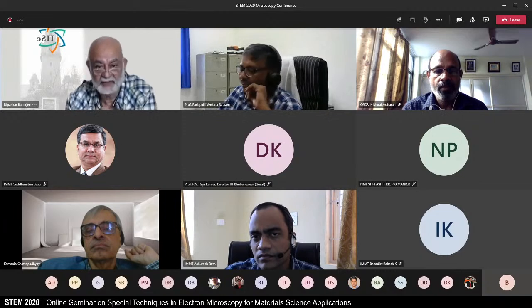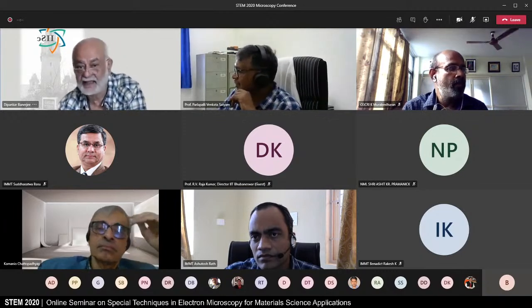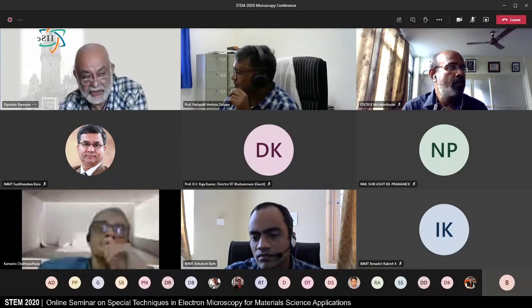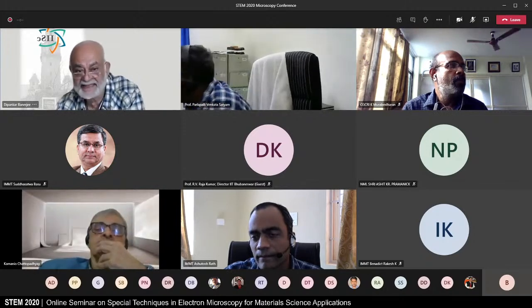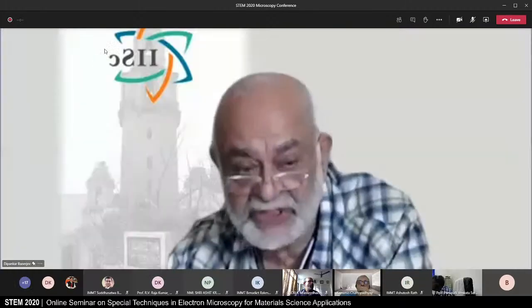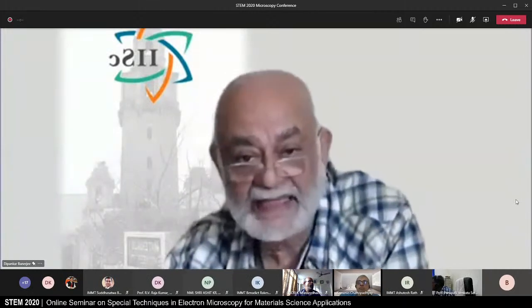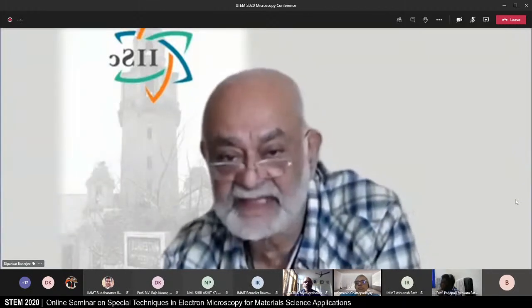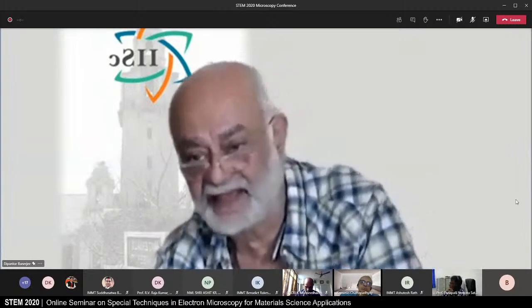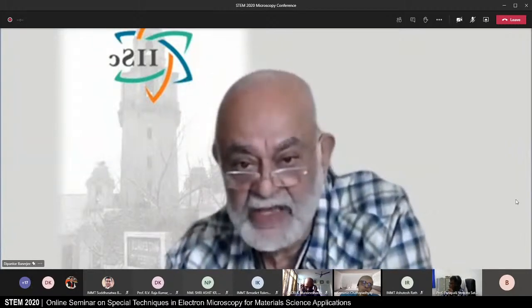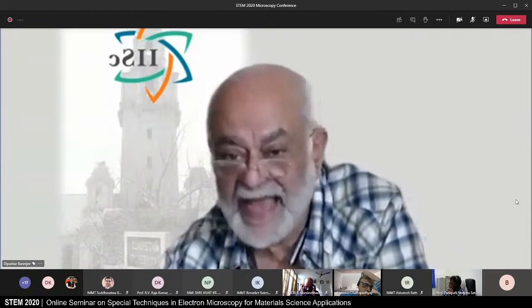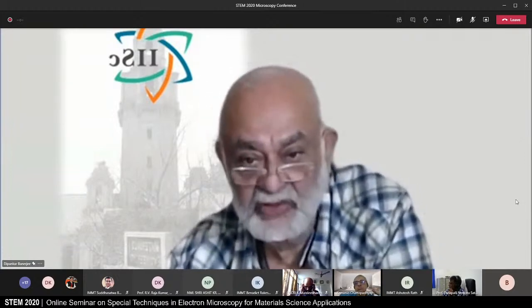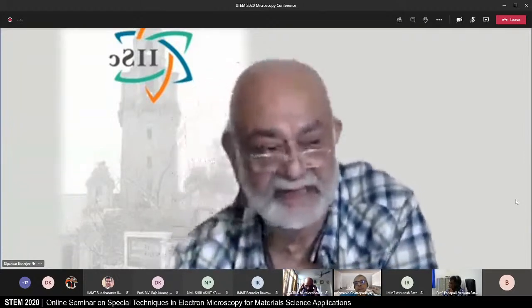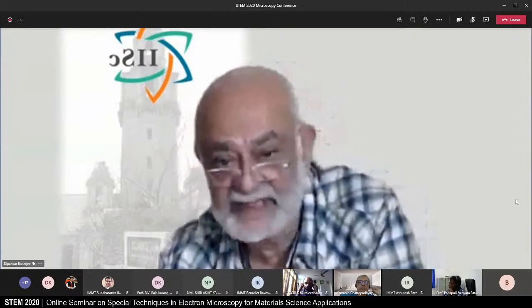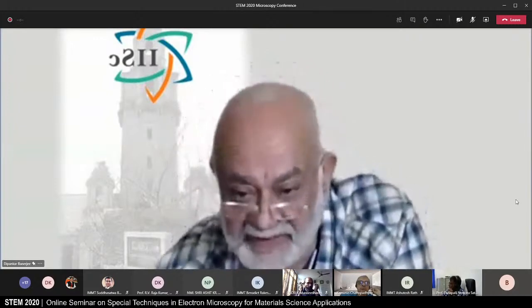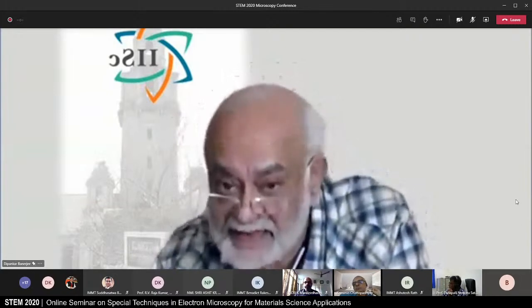In situ electron microscopy is again something that I did not touch upon, but you can today incorporate cells with certainly temperature, strain, and even reactions in special stages in the transmission electron microscope. So you can evaluate reactivity at the nanoscale. You can look at temperature effects on structure. You can look at stress effects and strain effects on the evolution of defects. So the answer is yes.